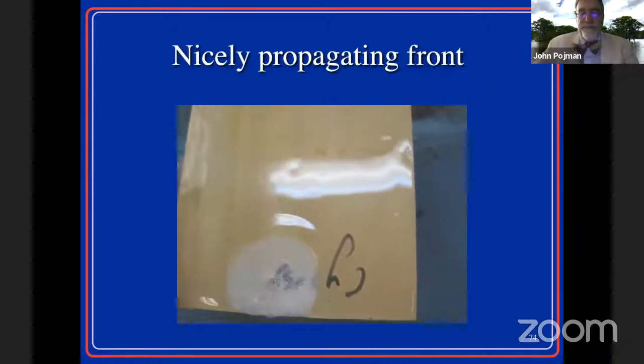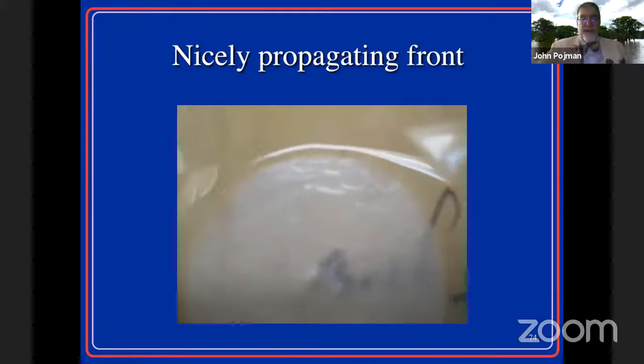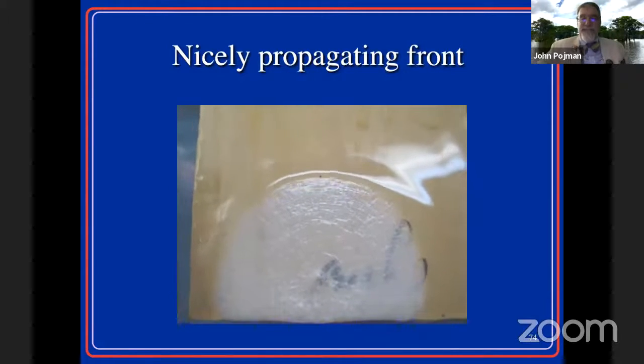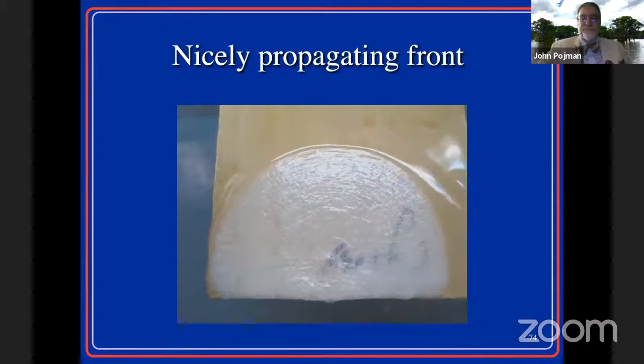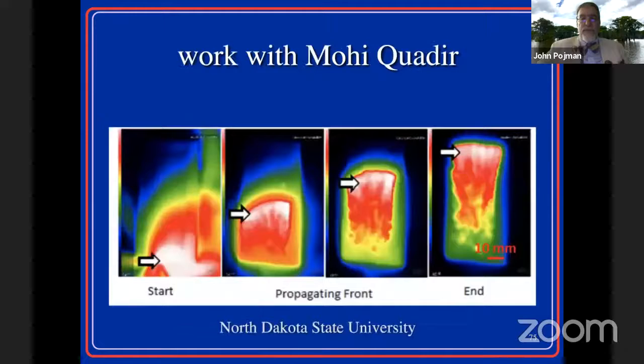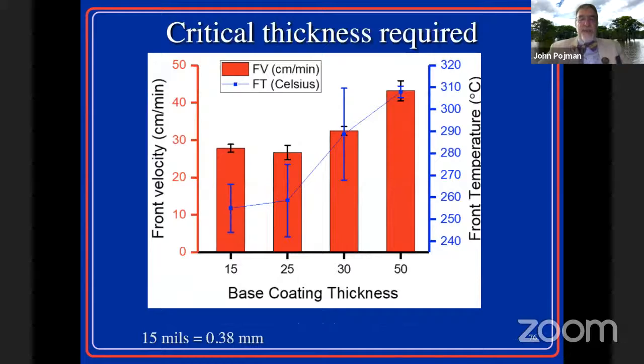So here's an early experiment I did myself 10 years ago. And we can see that we get this self-propagating reaction. So we started working with North Dakota State University, which has a long history working in coatings, to develop true coatings, not these couple millimeter thick layers, but real coatings, carefully controlled, and then be able to analyze their properties. This was done imaging with an infrared camera. This coating thickness is measured in something called mils. If you had something that was say 0.4 millimeters, pretty thin, we could get fronts that could still propagate pretty fast and get pretty high front temperatures.